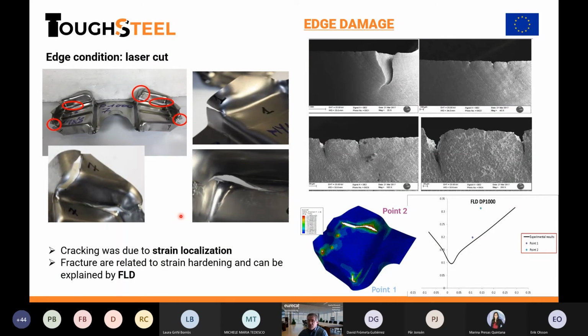This is a part that has been laser cut. So in principle, the edges are not so much affected. When these parts are formed, we see the cracks here, but these cracks are because of a strain localization. And these cracks, if we look at the FLD and the modeling, can be explained. This is where the part fails, and these points here are above our FLD. We look into the fracture. This is a strain localization. Okay, this is conventional formability, so FLD works.